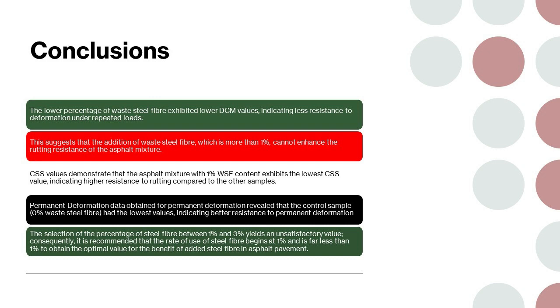CSS value demonstrates that the asphalt mixture with 1% WSF content exhibits the lowest CSS value, indicating higher resistance to rutting compared to the other samples. Previous studies also state that mixture susceptibility to pavement rutting corresponds to CSS, with the lowest CSS found in the mixture containing 1% steel fiber. This demonstrates that the mix with the lower CSS should resist rutting more.